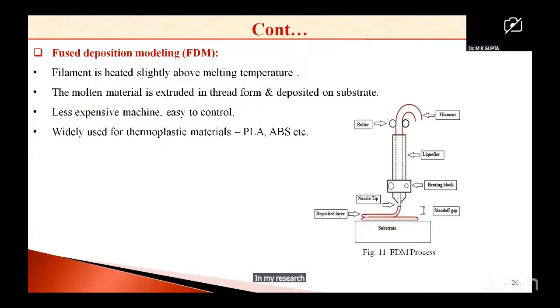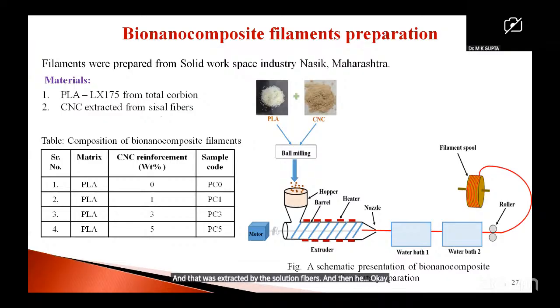One of my PhD students worked on it. He prepared the nano filaments using the nanocellulose that was extracted from sisal cellulose fibers, and then the nanocomposite filaments were prepared. In this work, as you can see, the PLA was the matrix and the CNC was extracted from the cellulose fiber. First of all, the filaments were prepared, and how were they prepared? Using the extruder.